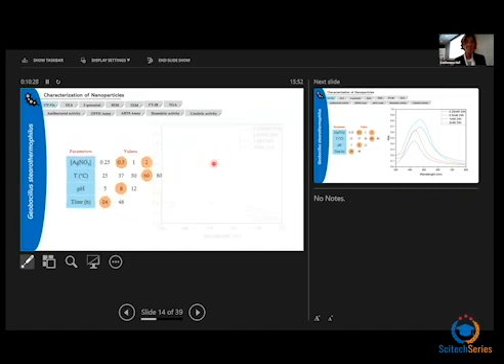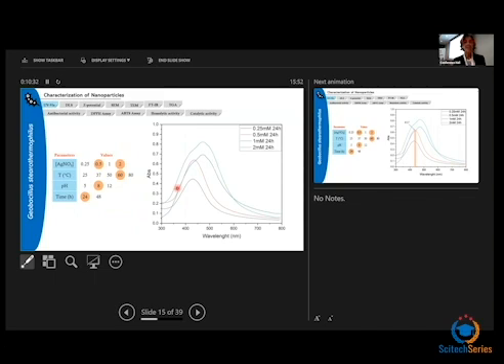The formation of the silver nanoparticles was verified by registering absorbance spectra that revealed typical surface plasmon resonance peaks with absorption maxima around 417 and 470 nanometers. Generally, peaks below this value can be considered associated with small spherical silver nanoparticles, whereas peaks above 430 nanometers are indicative of much bigger aggregates.